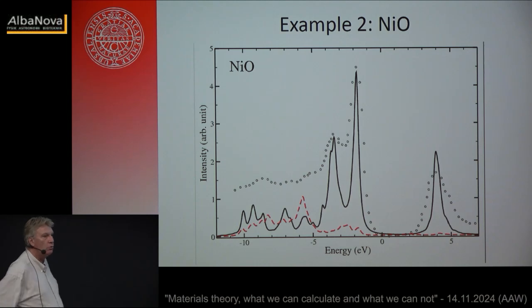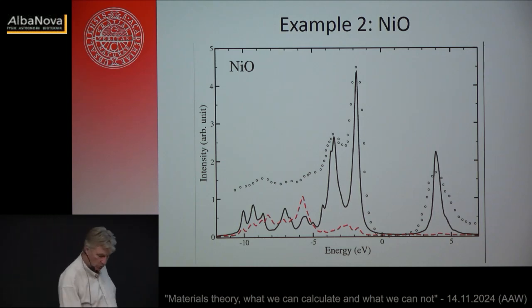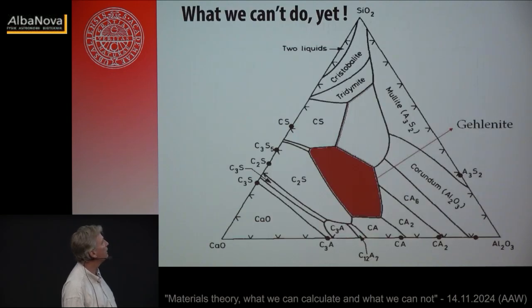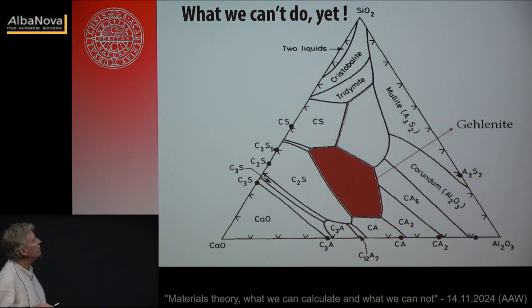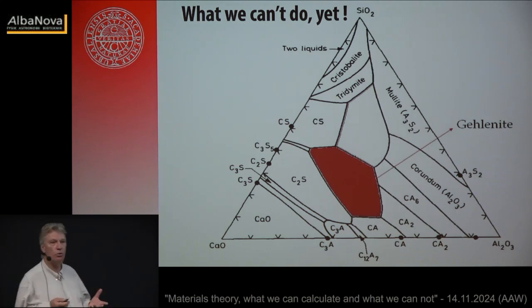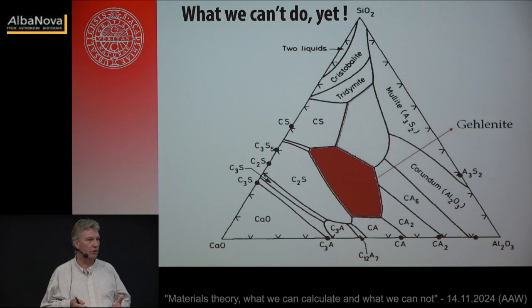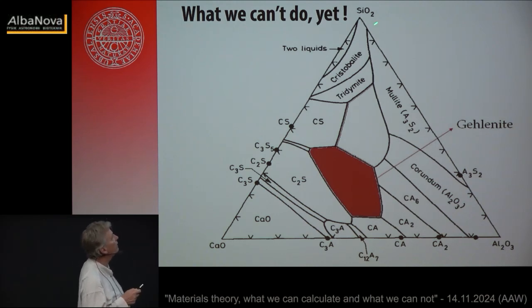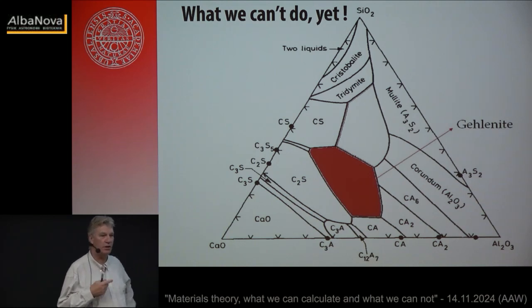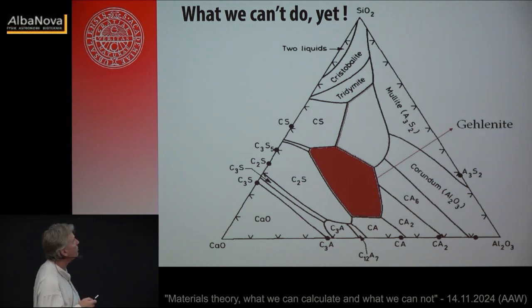But now I come to the failure that I promised, which is something that I would love to be able to do, and many of my experimental colleagues would also love for us to do, but we cannot. And that's represented here. If you're in the business of finding new materials, the first thing you do is you look at the phase diagram, what has been done before. Typically it's a ternary phase diagram, and this one is particularly delicate and complicated. It's silicon dioxide up here, calcium oxide down here, aluminum oxide Al2O3 here. It's a phase diagram very often used or relevant for people who are interested in glass and high purity glass. This is a phase diagram that has been identified by experimental means.